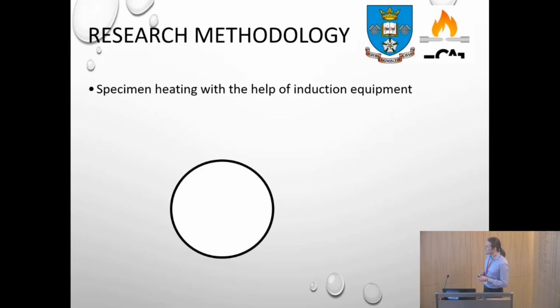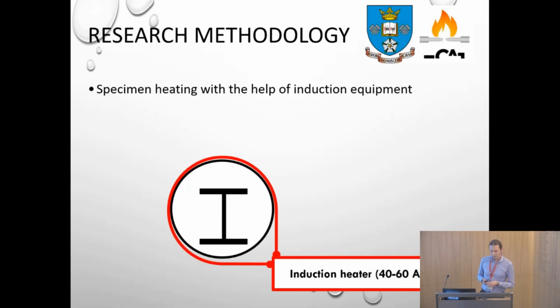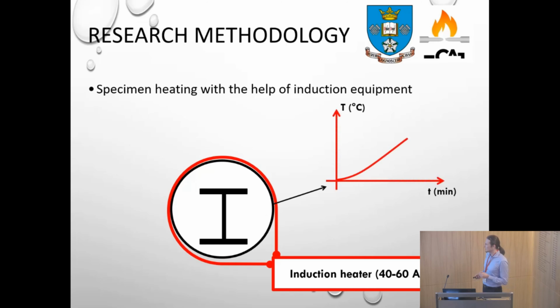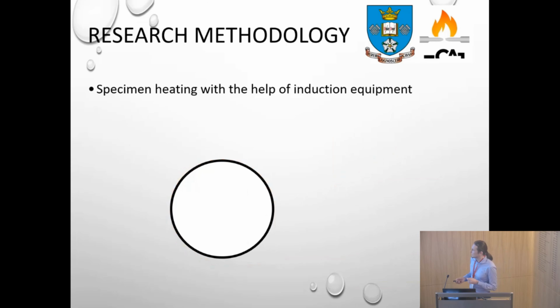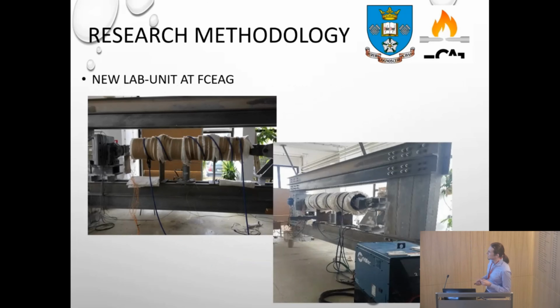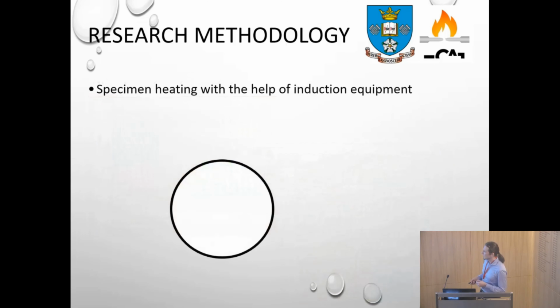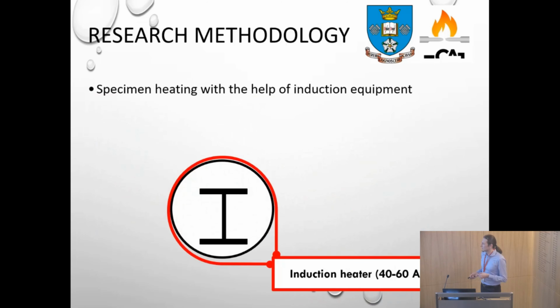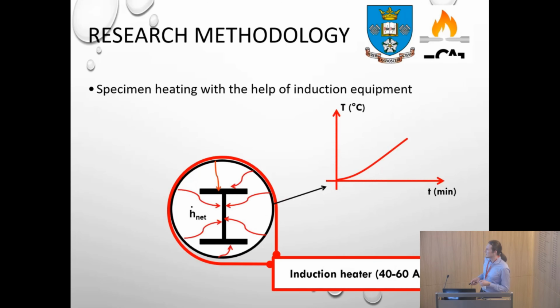The specifics of this test rig is that we use heating of this specimen by means of induction. That's something that we do by means of an industrial induction heater, which we wrap the cables around the tube itself, which you've seen on the figures here. The cables generate a high frequency electrical field, which heats the tube itself, and afterwards we can get the heating of the specimen inside by means of radiation and partially by convection.